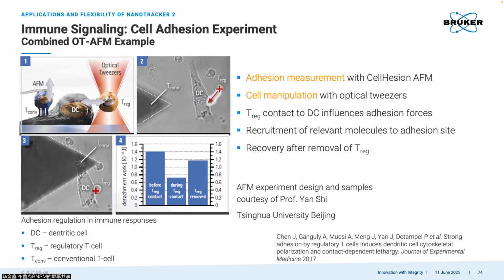So we go directly to this case. For this one, they have 3 cells. One is the Treg cell, then the second one is the DC cell here, and the third one is the T conventional cell here. The whole immune story is like this. When T regulatory cells combine with DC cells, it will suppress the immune response of the DC cells. And in this case, for the T conventional cells, the adhesion force between the T conventional cells and the DC cells will decrease. So for the whole experiment, they use the optical tweezer to trap the T regulatory cells and make a connection with the DC cells. And at the same time, they measure the adhesion force between the T conventional cell and the DC cell. They can see a dramatic decrease here.